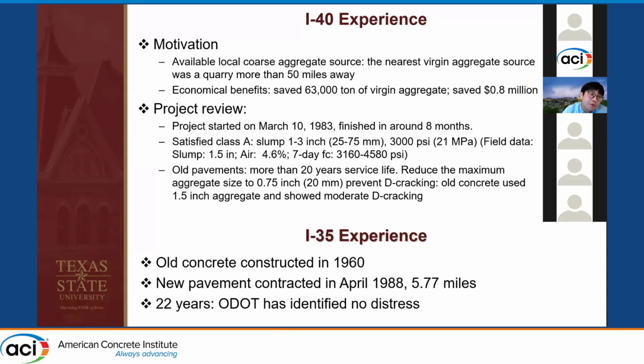And the contractor was able to produce satisfactory Class A concrete with 100% coarse RCA replacement. And the old concrete, which they recycled those RCA from, had more than 20 years of service life. The major problem with the old pavement was that it showed a severe D-cracking issue, and so to mitigate D-cracking from happening, the contractor decided to use smaller size aggregate for the newly built RCA concrete pavement.